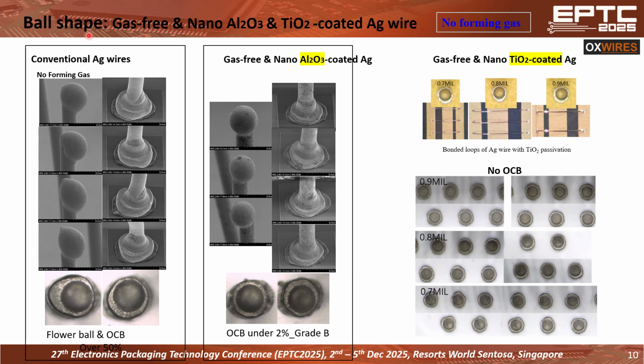Number one, ball shape. On your left-hand side, conventional Ag wires means that no passivation is applied. I'm going to emphasize that no forming gas was used. When we look at the ball shape, it's not very symmetric or round. But after we applied Al2O3 coating on the surfaces of the silver wire and TiO2 passivation coating on the surfaces of the silver wire, we got a very round ball shape at the bottom. On your right hand side, you can get a very nice loop out of 0.8 mil all the way up to 0.9 mil as well. There's no OCB because this passivation coating protects the surfaces of the silver wires from the oxidation and corrosion.